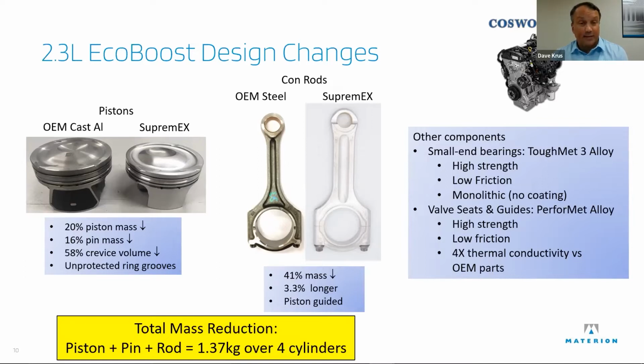Going back to that box at the bottom, the piston pin and rod, that's nearly 30% of the total weight of piston pins and rods. So you've taken out more than one cylinder's worth by reducing this weight. And the engine was not rebalanced and not recalibrated onto these materials, so it was out of balance and didn't take full advantage. We did see some friction gains, but the other thing was, everybody knows a 41% lighter con rod would work. Will it last?